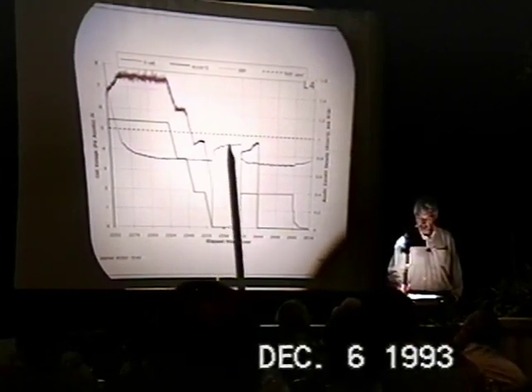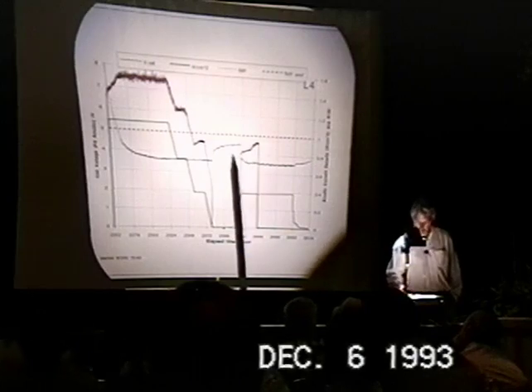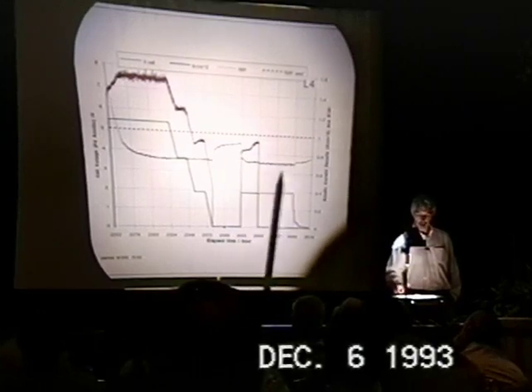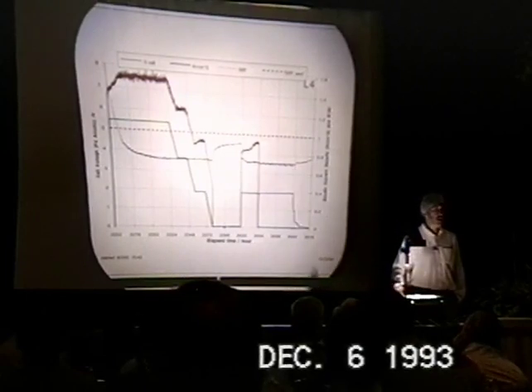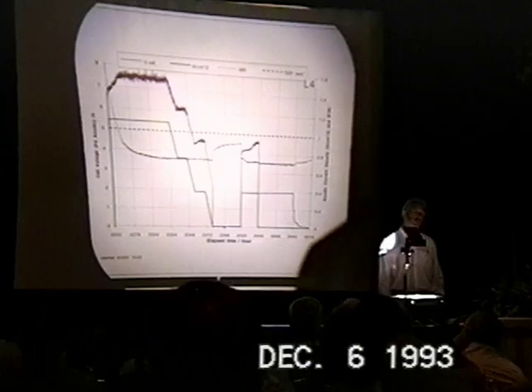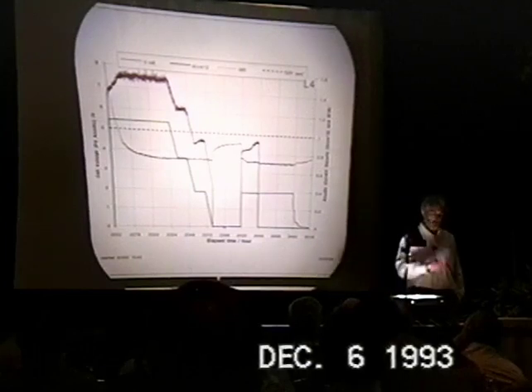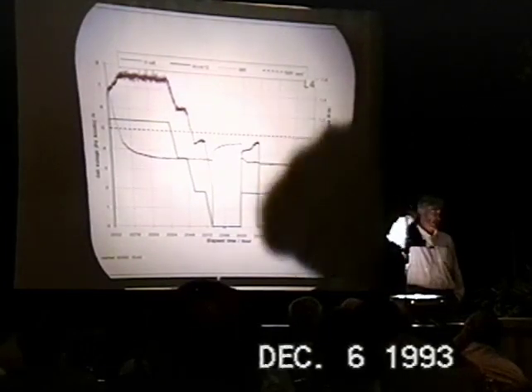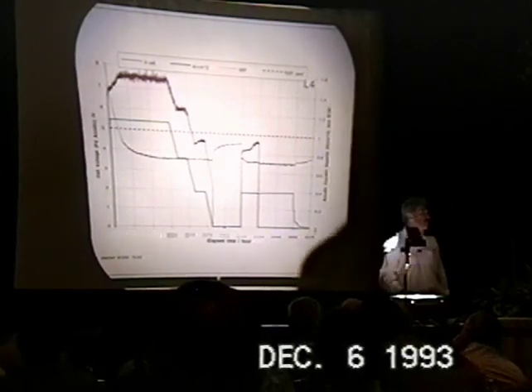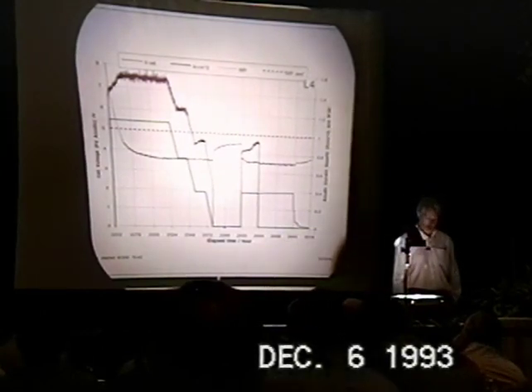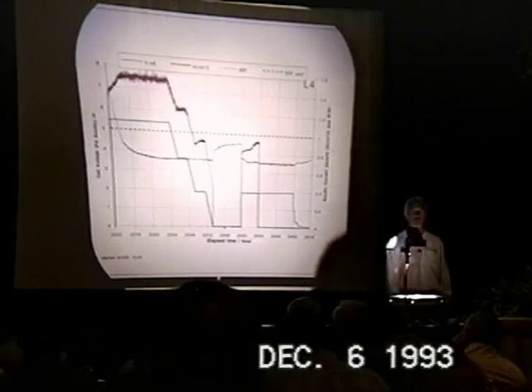the cathode reloaded again, we stripped it out again, this time more gently. And indeed, when we took this cathode out, cut all the wires off it, and measured it on the bench with the same instrument that we measured it with in the beginning, the resistance of this particular piece of palladium at the end of the experiment is only 0.7 of its value at the beginning. For this, I have no explanation. Thank you.